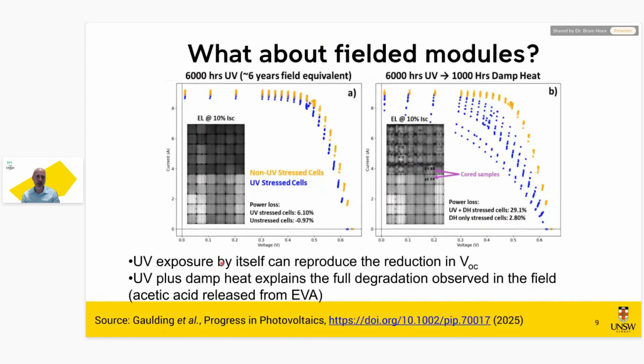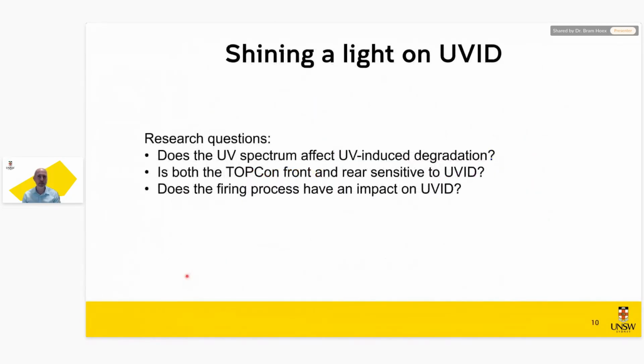So UV-induced degradation can also affect the encapsulant. And in this case, the encapsulant was releasing acetic acid that resulted in series resistance issues. So this really shows that combined stress testing is definitely something we have to move towards as a sector. I will not show it in this presentation, but it's something I'm quite passionate about, and it's definitely something that's shared also by Sinovoltaics and the great group at NREL.